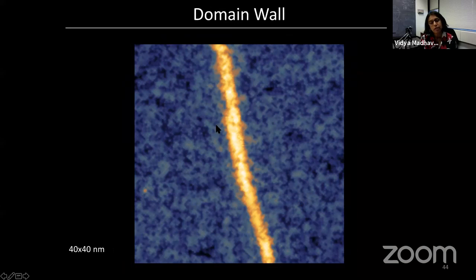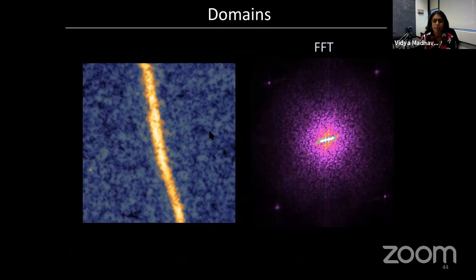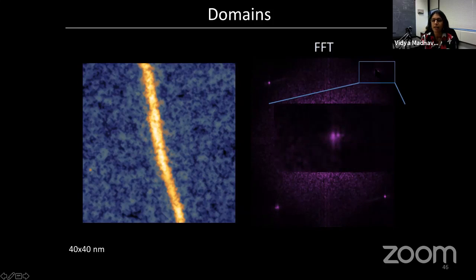And if you zoomed into one of these, here's a domain wall. By the way, you can have many different one-dimensional features. So not all features that look like that are domain walls, but we can check with STM. If you zoom into one of these, you can do a Fourier transform. And if this region is shifted from this region by a half a unit cell, then you see it in the Fourier transform by a splitting of the Fourier transform peaks. So that's what you can see here.